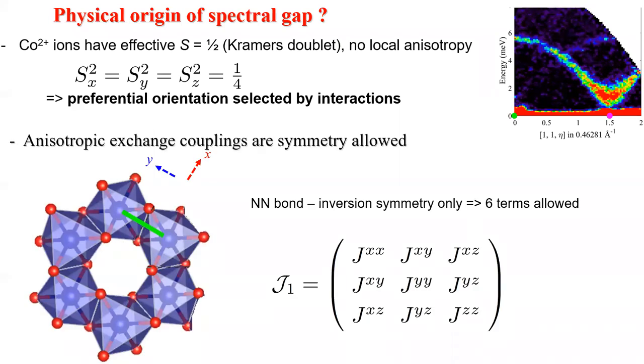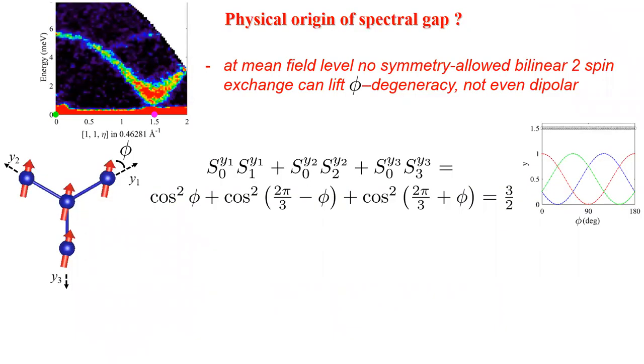single-ion anisotropy. Now, of course, we've assumed a very simplified form of interaction, in which the interaction matrix is diagonal, and the x and y parts are the same. Now, for the actual material, many other anisotropic terms are allowed because the middle of the nearest neighbor bond only has inversion symmetry. In principle, all the symmetric types of exchanges are allowed. So we'll first look at the most obvious anisotropy, which is the exchange difference between components along the bond and perpendicular.